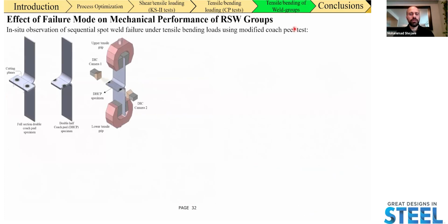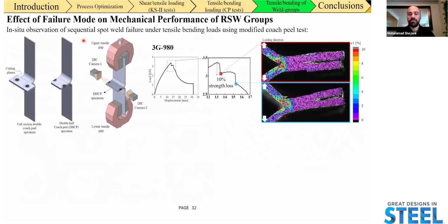Now, in order to understand how the failure behavior is actually affecting our mechanical performance, we also performed a modified version of the coach peel test that allows us to see in situ the evolution of the strain, or the failure, that is happening throughout the test. We sectioned the welds in half to allow a window for DIC observation.